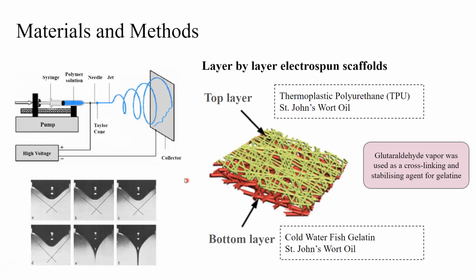In this study, a layer by layer structure was produced as two different polymer solutions were electrospun in a row. The first polymer solution basically includes thermoplastic polyurethane and St. John's wort oil. For the first layer, this polymer solution was electrospun under preset conditions. Then, a second polymer solution, which includes gelatin and St. John's wort oil, was electrospun above the first layer, as schematically represented here.